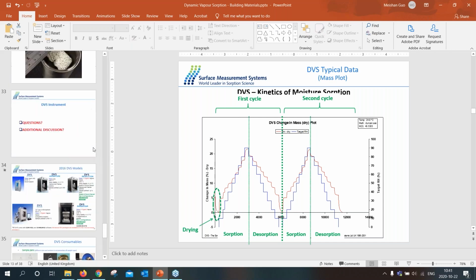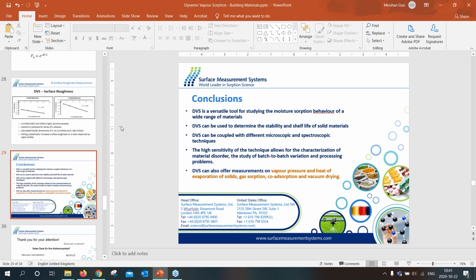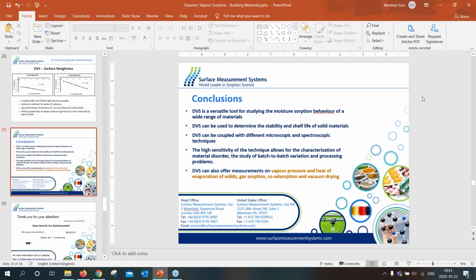Actually, we have some studies for the wood sample. Sorry, but because of the time limit, I didn't show it here. We do have measurements of different natures or different geometries of the wood samples, measuring the water sorption uptake. It shows that a powder sample, because it has a faster diffusion behavior, will reach a better equilibrium and give better kinetics data. The uptake is also higher compared to a solid or trunk sample, or a block sample. Those take a longer time to reach equilibrium, and the uptake will also be lower. So the geometry or different forms of the sample will affect the behavior of moisture sorption, and this can be detected by our DVS data or from the DVS experiment.